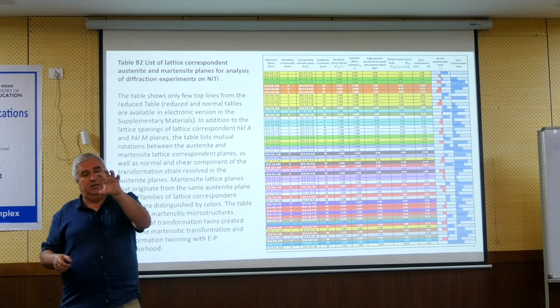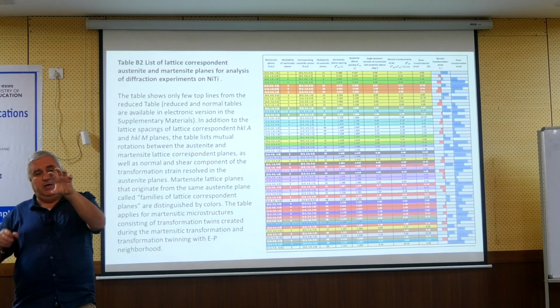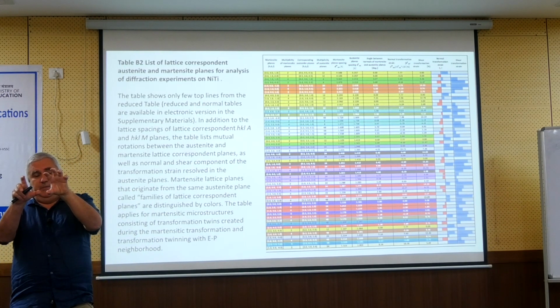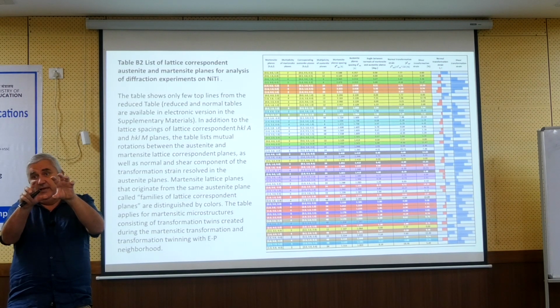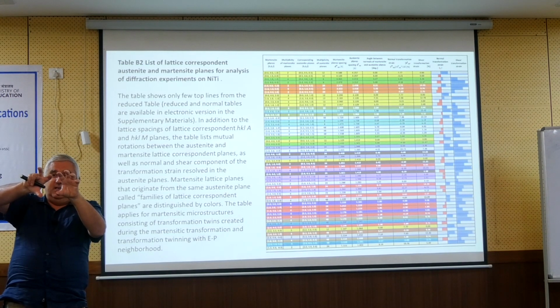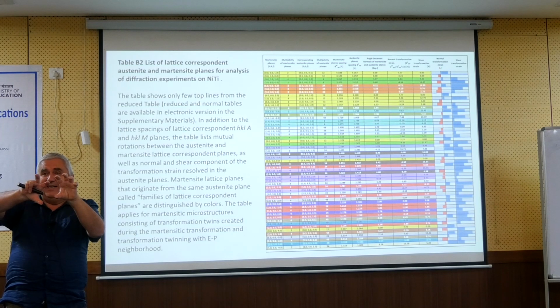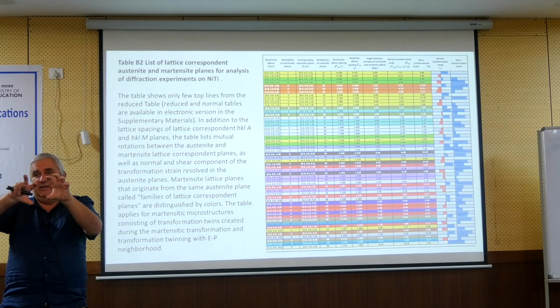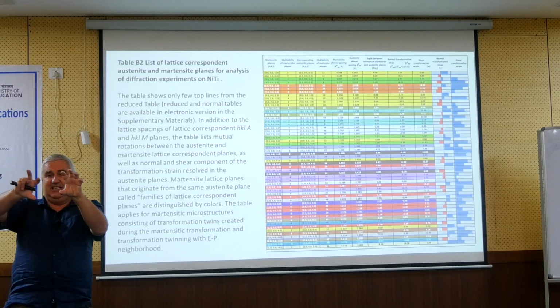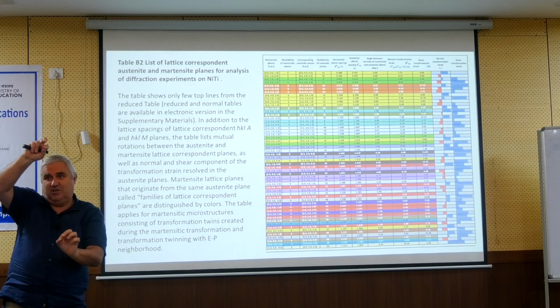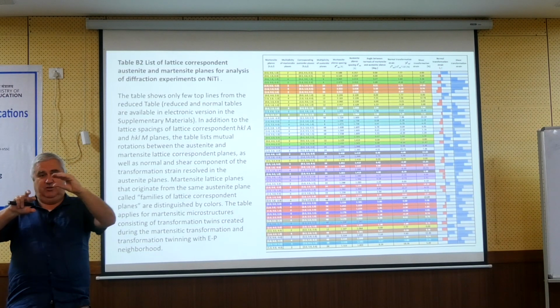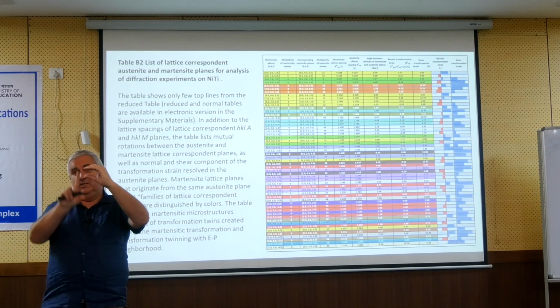Okay, so this is the austenite cube, and now the martensite lattice, which is basically a strained austenite, where the shape strain is applied, is rotated in such a way that the long 001 axis is aligned with this 011. So your question is basically irrelevant. You have one lattice, a second lattice, and this is about how it is rotated. So it is extension along this direction. If I have these planes, it's always along this direction.